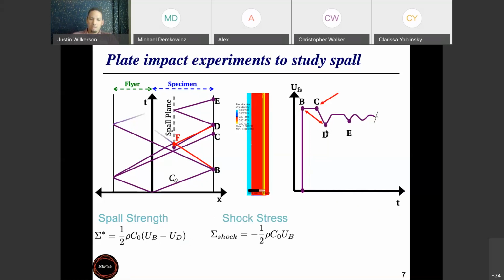In addition to that, a very important metric is the shock stress, which is basically the magnitude of the compressive stress that the shock wave induced when it first propagated through the material. The reason that that's important is because that is essentially going to cause microstructure evolution when the shock first goes by. It's going to generate a bunch of dislocations. It may heat up the material. It will heat up the material a bit. If the shock stress is high, it can heat up the material quite a bit.